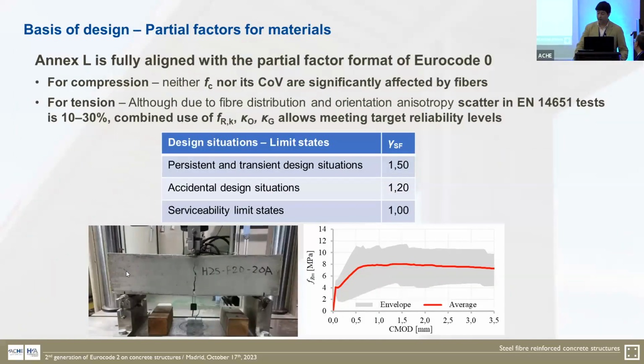Regarding the safety format, the design also follows the partial safety format approach. The safety coefficients accepted for the concrete, for compressive and tensile pre-crack and residual tensile strength, are 1.5, 1.20 in case of accidental loads, and 1 for the serviceability limit state. I want to highlight that even with the high variability that the post-cracking strength of fiber reinforced concrete can have, which can vary between 10 and 30%, these coefficients are sufficient for guaranteeing the reliability index of 3.8 that has been accepted.